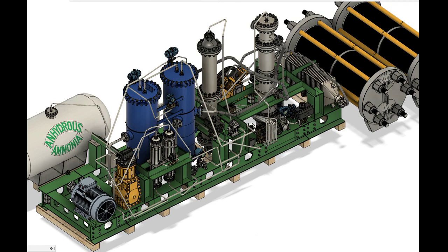Assuming an alloy price of $1,500 per ton, we arrive at $378,000 for material costs alone. Fabrication is difficult to estimate as no literature to date has been published on ammonia converter fabrication costs. We estimate a conservative material fraction of 25%, yielding $1,512,000 for the converter, but the real number is most likely substantially higher, since most converters are manufactured by Western firms in high labor rate countries.